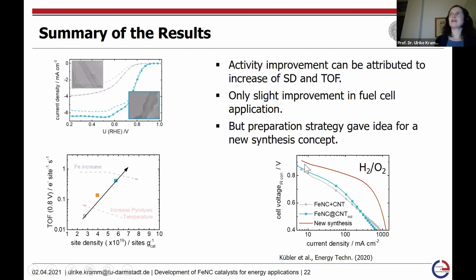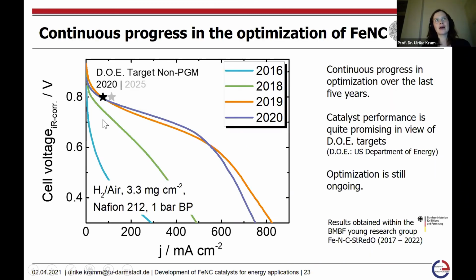So for the Fe-N-C, we do not see it quite above 1 volt. What you can observe is that, of course, you have a dependence on the humidity of the system. And these were some tests that were quite in the early times after setting up our fuel cell system, so probably it was not fully optimized. We still do not see, even when we go for hydrogen-air application, that it goes up to 1 volt, but it depends a lot on the measurement conditions and the setups that we are using. Is it because you might have perhydroxyl ions in the open circuit conditions?